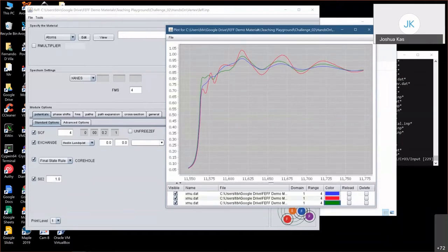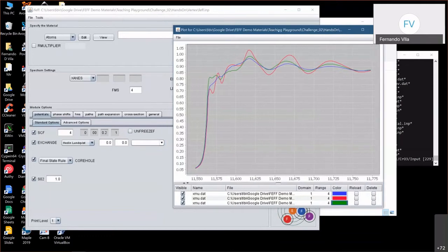I assume that you basically told them that in this particular case, we are using exactly the same FMS and SCF radius in all the calculations to make everything very nicely consistent. And basically, we try to encapsulate the whole nanoparticle. In that case, this is possible. If you had a system that was a nanoparticle that was larger, like in the nanometer range, you probably would have to do the same kind of tricks that you would normally do, which is test for convergence with respect to FMS and SCF radius.